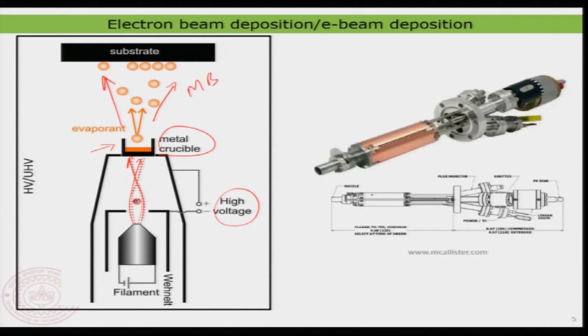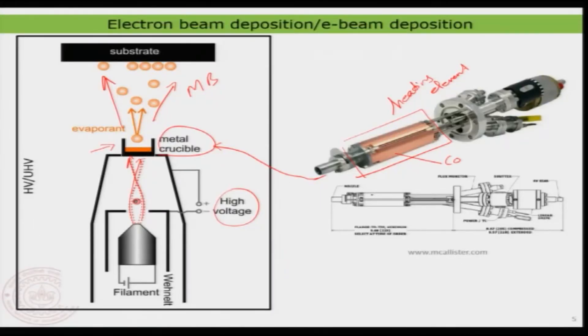To show how this looks experimentally: the crucible is made of molybdenum, and the heating elements are placed inside while electrons are bombarded from the back side through the heating element. Since a lot of heat is generated, the exterior of the electron bombardment chamber is cooled using copper plates. This cooling allows the evaporation to proceed nicely. This is an efficient technique for evaporating materials with very high melting points, though the sputtering technique is generally the most preferred overall.